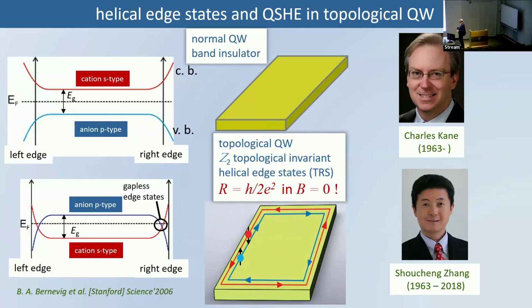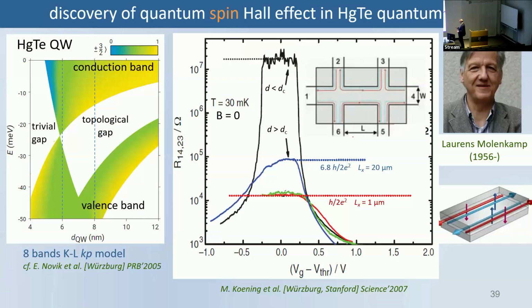What does the experiment tell? The experiment is shown here. And what you see is that if you have a very thin sample of this mercury telluride, you expect a trivial gap, where S states pushed by confinement are very high, P states are lower, and you have a trivial situation. And nothing special happens. You have infinite resistance if your Fermi energy is tuned through the energy gap here. But the situation changes here. If you now have a topological situation, you have these edge states, and you see that you have non-infinite but finite resistance here, Hall resistance.